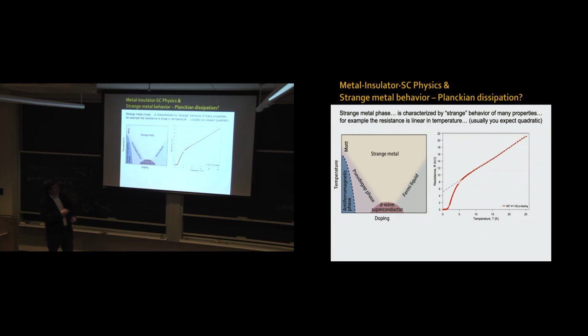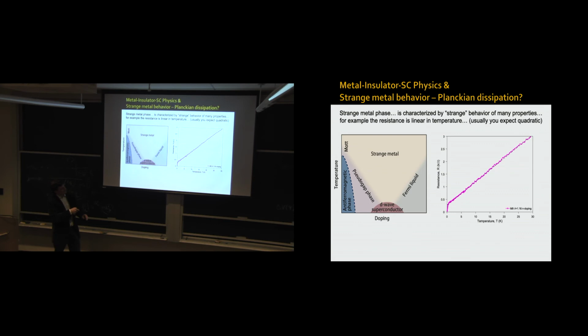In our system, if we take the resistivity, we have superconductivity at low temperature, and then this linear resistivity with temperature. Because this is relatively high TC, this behavior is interrupted, but we can take another sample where TC is much smaller, and then we see this linear resistivity behavior down to almost zero temperature. This temperature, around 25-30 Kelvin, may not seem large compared to the cuprates, but remember, this is an ultra low density system - the Fermi temperature is about 30 Kelvin, so this range is equivalent to reaching several thousand Kelvin for the cuprates.